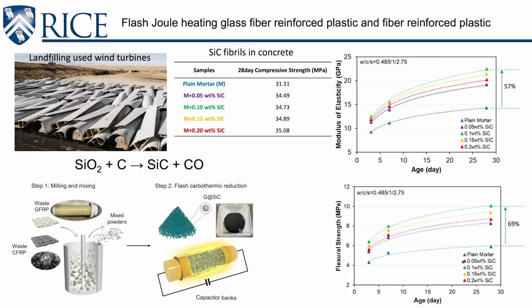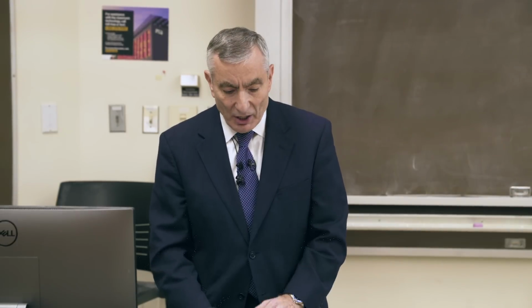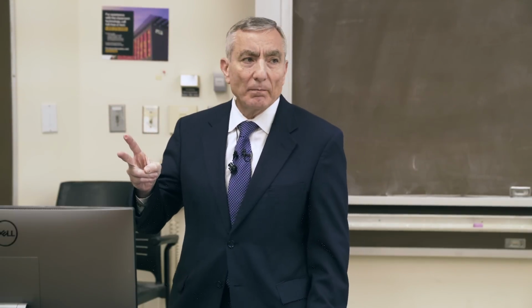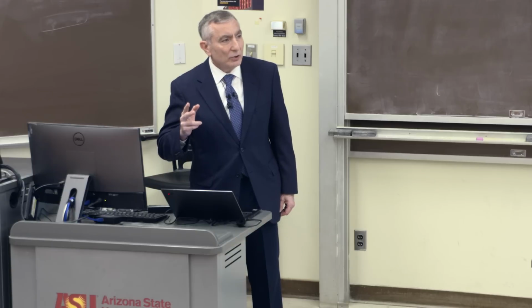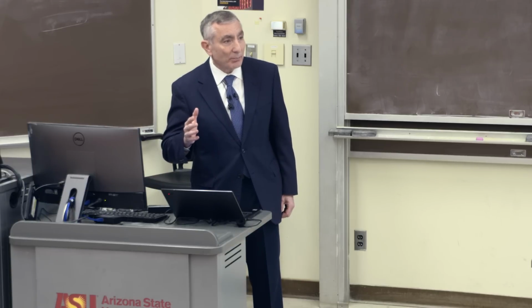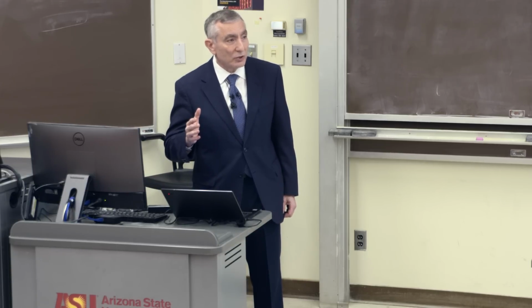At 0.1 weight percent addition to the cement in concrete, you get a 69% improvement in the flexural strength, and a 57% improvement in the modulus of elasticity. So you see these effects here, so you can make new materials and use this in an environmentally nice way. Well, when you flash, say, polyethylene or polypropylene, there are 2 hydrogens for every carbon atom. What happens to those hydrogen atoms, I wonder? Well, you turn that carbon material, that polyethylene, polypropylene, into graphene.